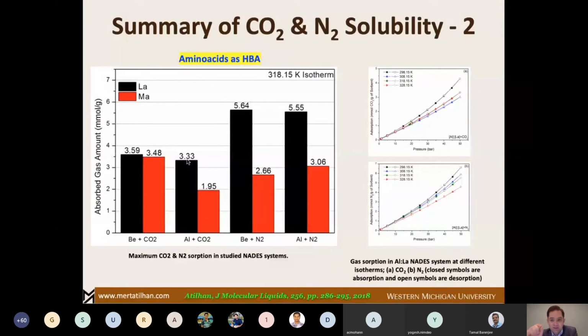One thing that we specifically observed here was the absorption and desorption curves. Many people don't really report on the absorption desorption, because I believe that this is quite essential and very crucial information for us to be able to see how a solvent behaves in the case of releasing the pressure. Because most of the time you see hysteresis. So when the hysteresis happens, it means that you might have very complex dynamics in the column.